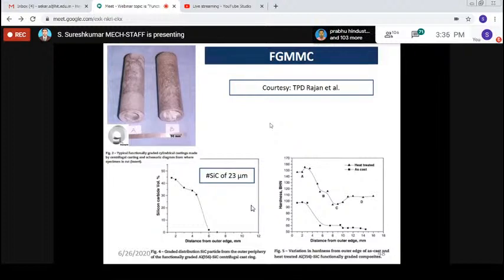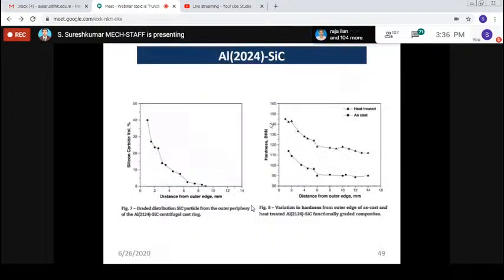The silicon carbide particle size used for fabrication is 23 micrometers. And again, similar things are reported for some other composites, an aluminum alloy reinforced with silicon carbide. In this case again, it is gradually decreasing, and the hardness value also. So when you are moving towards the inner periphery of the hollow cylinder, the reinforcement is being reduced.